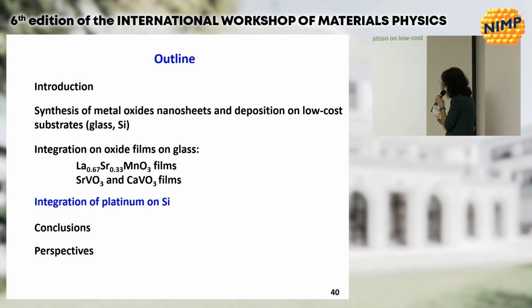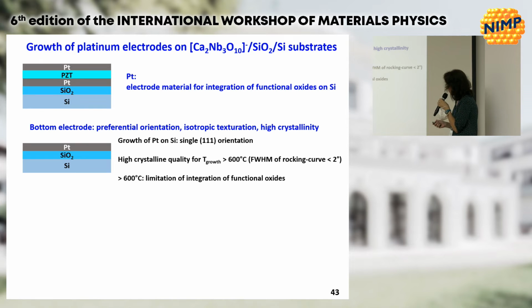I didn't talk about integration of oxide on silicon yet. We have some results, but I will now move to something else, which is integration of platinum on silicon. As you know, platinum is an electrode material for integration of functional oxides on silicon. We can have it as a bottom electrode or as a top electrode. For the bottom electrode, a preferential orientation is needed, an isotropic texturation, and high crystallinity are also required. The natural growth of platinum on silicon is in a 111 orientation, and to obtain a very good electrode, we need to grow at higher than 600 degrees with a very small rocking curve width. But the problem is that this is also the limitation for the integration of functional oxides in microelectronics.